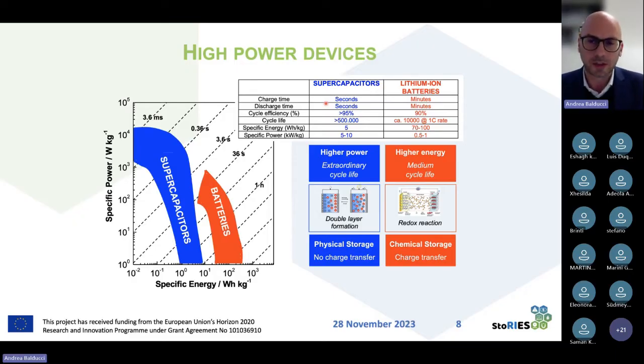As we mentioned before, the energy of the lithium-ion battery is significantly higher than that of the supercapacitor. We are talking about one order of magnitude of difference in terms of energy. On the other hand, the power of supercapacitors is more or less one order of magnitude higher than that of a lithium-ion battery. So what we have is really a difference in the main properties of these two devices. Supercapacitors are high power systems which have a very high cycle life, much higher than that of the lithium-ion